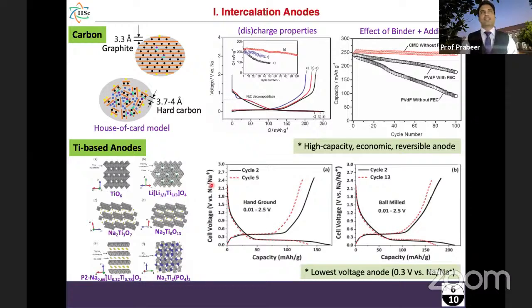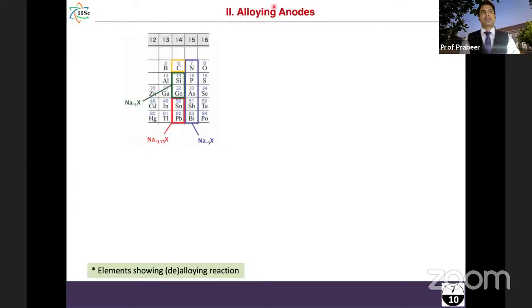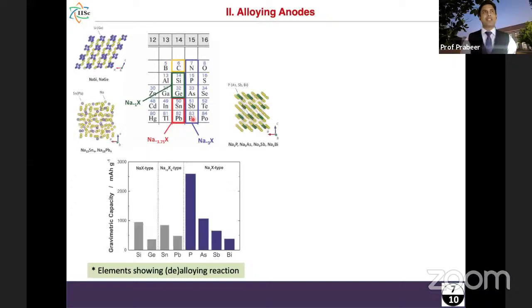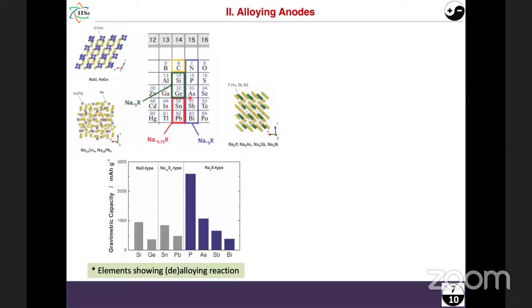Now moving on, the second class is the alloying anodes. So if we see this portion of the periodic table, carbon is the hard carbon, forget it, but below that, in these intermetallic semi-metallic components, it is possible that sodium can react: one sodium can react with silicon, germanium, around 3.75 sodium can react in it, and around 3 sodium can react with antimony, bismuth, and so on. As a result, it can form different kinds of alloys with all these elements, group 14 and 15 elements.